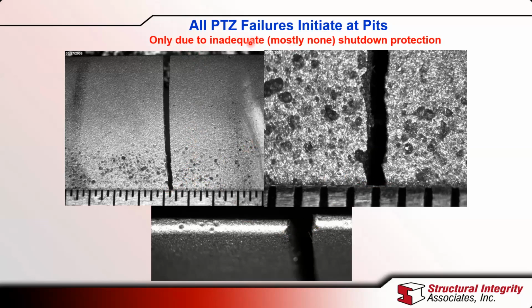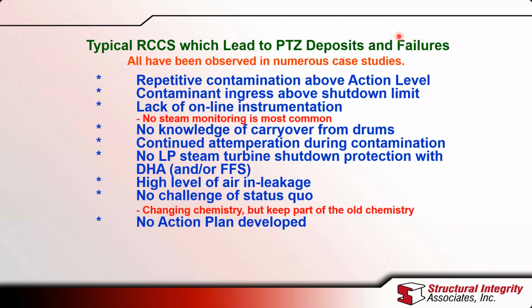there is some inadequacy of shutdown protection. Most often we find that there's no protection in terms of adding dehumidified air to the low pressure turbine. So these are very common, and these are the typical cycle chemistry situations which lead to phase transition zone failures. So hopefully by now you get the idea that if you allow the chemistry to operate with these RCCS, then there's a good possibility that you will have these failures taking place.